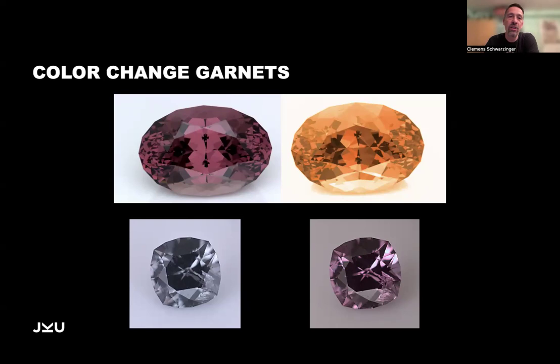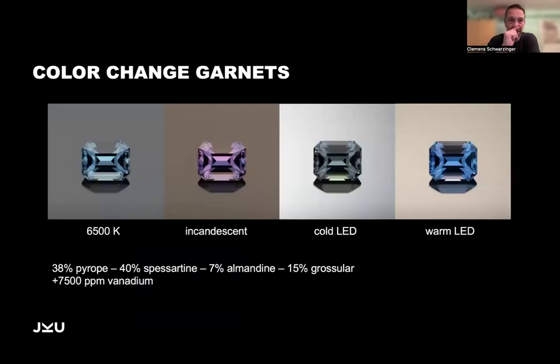An extreme color change is what I can show you here. This is a garnet that I had in my hands 2 years ago. And we did also write some article on this one. So this was photographed with 6,500 Kelvin, which is close to daylight equivalent, with some incandescent light and with 2 different LED lights, cold and warm LED lights. And you can see that it goes from a steely blue to purple to a greenish gray to a perfect blue. And this perfect blue was also, this is the best description of what the stone had in natural sunlight,